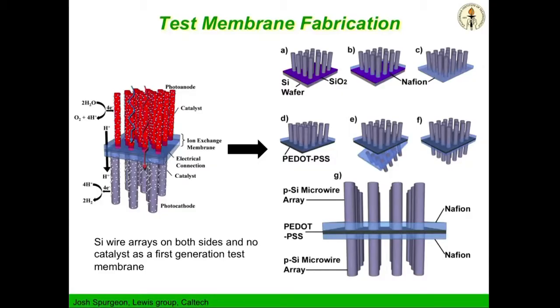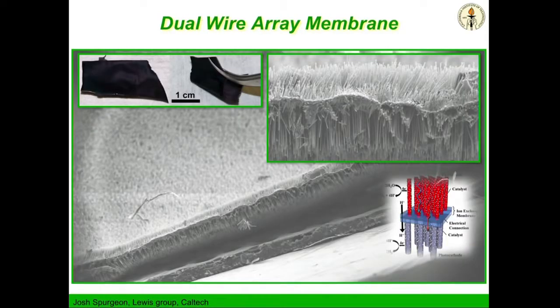And we transfer that problem into a soft materials problem. We do it by growing one material and then doing another, peeling them off, and then laminating them like making a driver's license. To demonstrate this structure, which is PowerPoint, we made all these ingredients. We made a peeled bottom layer, made a peeled top layer, made an intervening layer that made ohmic contacts. Here's that structure. You can hold it in your hand. It looks now like the PowerPoint that we had 4 years ago.